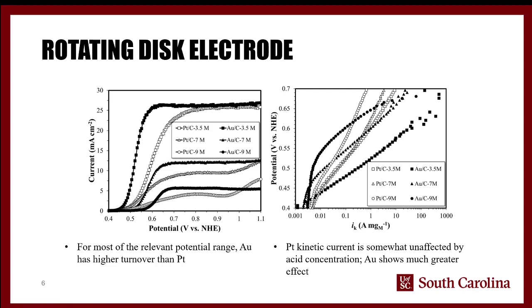Now, the fact that they both drop off means one of two things. Either the catalyst itself is affected by the higher amount of sulfate present, and or the diffusion of the reactant is slower. We know the viscosity of sulfuric acid is higher than that of water, so the diffusion aspect is one part of it. However, because we're using a rotating disc electrode, we also know that at the steady state value at least, diffusion is no longer the limiting factor. If you spin a rotating disc electrode fast enough, you hit a limiting steady state current, and that lets you compare two materials even when diffusion is changing depending on your electrolyte.